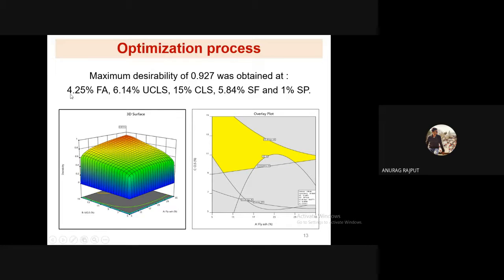These are the input variables. These are the dosage levels which the software gives us, which enhance the strength. This is the plot where we can have the desirability of 0.927. This is the 3D surface plot. We can use our fly ash in the range and uncalcined limestone in the same range. So maximum utilization of uncalcined limestone and calcined limestone was there along with the silica fume and fly ash.